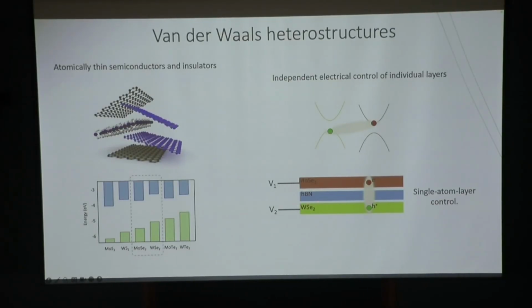And we use a thin boron nitride as the dielectric barrier. This boron nitride we can control with single-layer precision. So we can decide whether we want a 5-layer dielectric or a 6-layer dielectric, depending on the device configuration that we want. And then we will dope electrons and holes in the semiconducting layers, where the electron-hole recombination will be suppressed by the boron nitride, and they can live for very long.